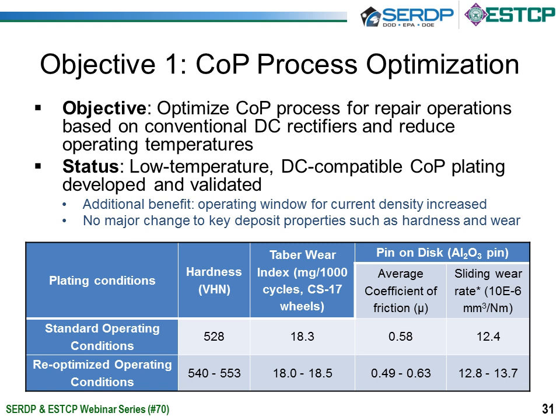And then through that, we were able to identify a window of operation that results in being able to plate at slightly lower temperature as well as using direct current as opposed to pulse plating. And this is mainly due to the addition of some chemistry and some additives. But the big benefit is now there's a nice, slightly enhanced operating window for lower temperature, as well as increased current density and direct current plating.